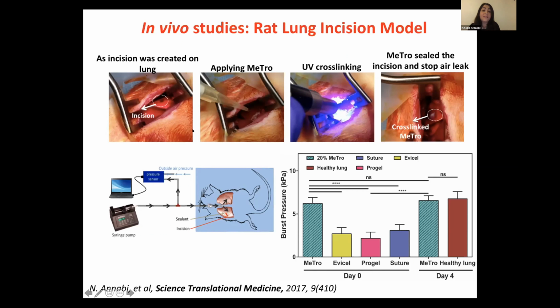So we form the same size defect, seal it with Metro and different types of commercial glue. And also we close the defect by suturing. And we show that for all these conventional methods, and even the use of the best surgical material on the market, Progel, the burst pressure was much lower compared to our optimized formulation of Metro. And then after treating the defect in the lung with all these formulations, we kept the animals, and after 4 days, we sacrificed the animals and ran the burst pressure again. And what we observed for the MetroSeal lung, the burst pressure was very close to the healthy lung. Basically, Metro sealed the defect and stopped the air leakages at the beginning, but over time it also helped regeneration of the defect site that we formed on the lung.